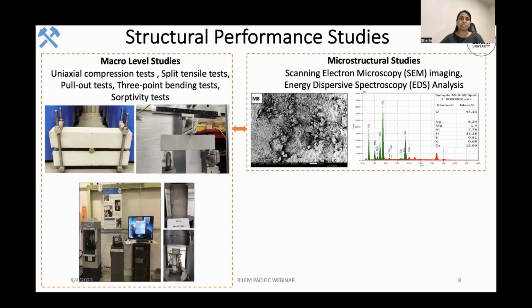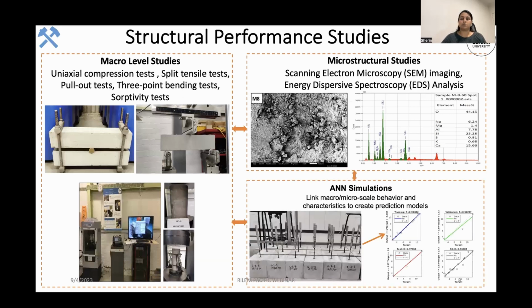Also, the microstructural studies conducted on specimens immersed in various conditions help us to identify whether there is any chemical ingress or whether there is any salt formation, and what is the quantification of these amounts of salts within that certain specimen. These studies were then linked together to create a holistic picture of the performance of this particular self-compacting geopolymer concrete when reinforced with bars.